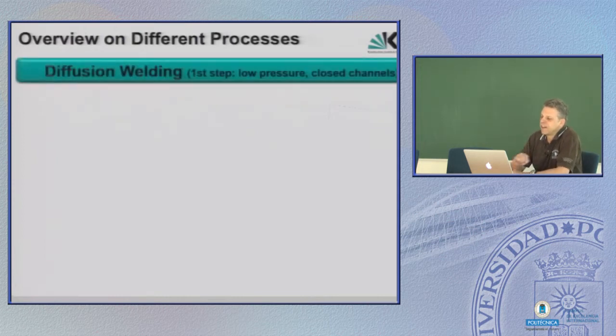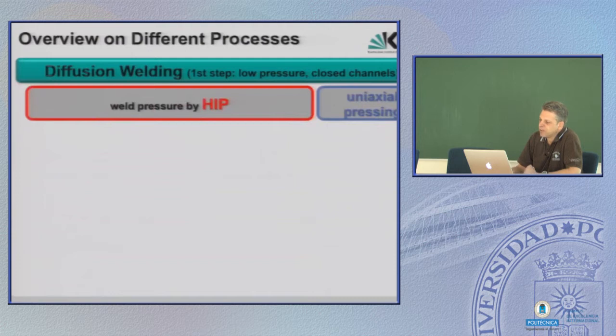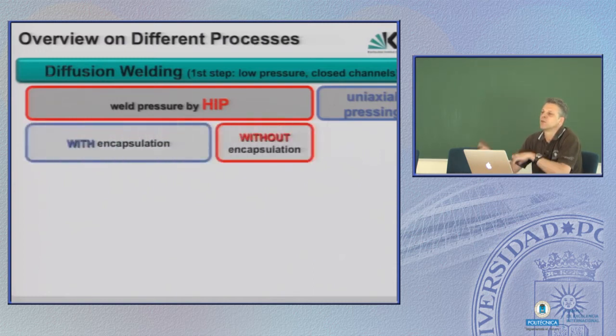Diffusion welding, in that case, could be done as you have seen in the first picture. You produce the first wall in 2 halves, 2 plates. Then you can fabricate half of the grooves or cooling channels in each plate, and you have more or less to glue both halves of the first wall together, and then you end up with a complete tight cooling channel. That's the theory. So one step would be diffusion welding of such two half parts for the first wall, and start with a low pressure step to close the cooling channels. Then the weld is pressured either by hot isostatic pressing, or you could also just press the plates together by a big press in a furnace. That's uniaxial pressing.